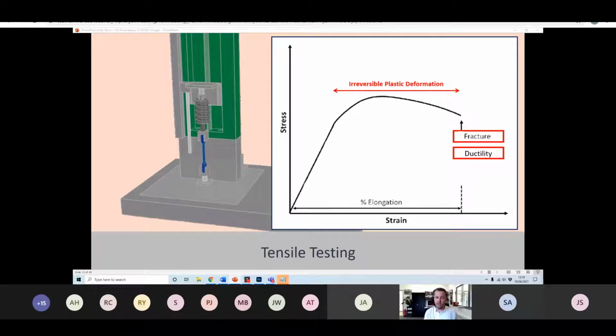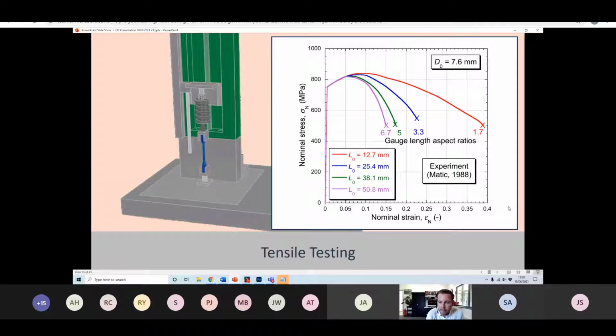The ductility that is measured in a normal tensile test actually varies, it changes, if you change the dimension of the test coupon that you use. And I know from my conversations with people in and around the various industries we work with, and also in the universities that we work with, that this is not always appreciated. But it's extremely important to understand and recognize this. And I'll explain why. So here are some real experimental tensile test data, all being conducted on the same material. Okay, and this data shows that the ductility value falls as the specimen aspect ratio increases. Now, the curves are actually almost coincident up to the ultimate tensile strength, and that's exactly what should happen. That's exactly how it should be.